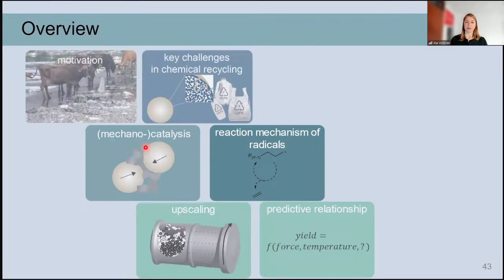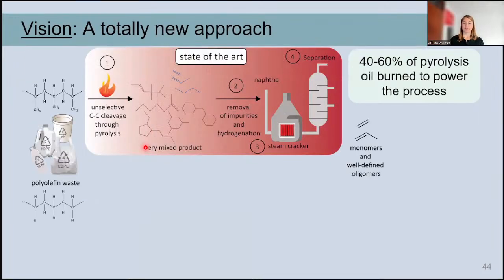So with that, I would like to move a bit into the future and look at upscaling. And so with the state of the art, as I explained, the vision is that we can improve this process. So with the state of the art for polyolefin conversion, we have to work at very high temperatures, which leads to very unselective reaction with a lot of mixed product that then has to also be cleaned up, because usually plastic waste has impurities, and then it can be sent to the steam cracker. And after that, it still needs to be separated to obtain the monomers. And with this, the whole efficiency of the process is only around 50% because of all the fuel that we have to burn to power these processes.